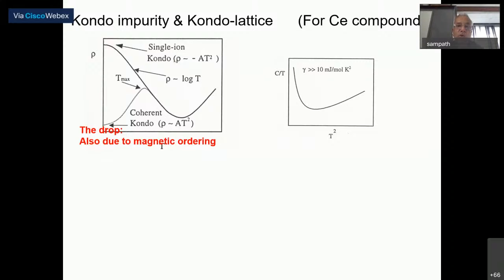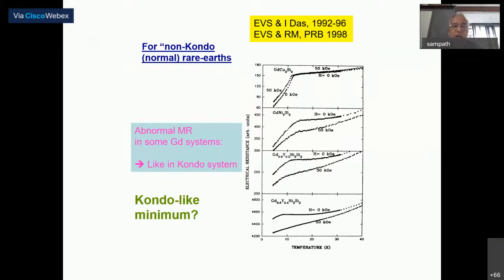at that time. So now, when you come to gadolinium compounds, what we have done is, as I already mentioned, look at a somewhat simple system where you don't expect the Kondo effect. You know, in the case of gadolinium, you don't expect the Kondo effect. The main reason is that the 4f orbital is strictly localized. The energy position relative to the Fermi level is a few electron volts below the Fermi level. There will be very little scope for that electron to come out, go to the conduction band, come back, or to hybridize. Therefore, this interaction is virtually negligible. Therefore, you don't expect these kinds of features except for cerium compounds.